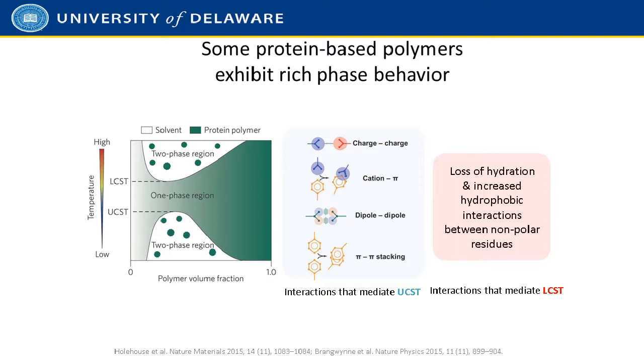If we go back to the one-phase region and instead increase temperature, one traverses the lower critical solution temperature, in which phase separation occurs as a generally hydrophobic molecule becomes less solvated and then forms a polymer-rich phase inside a solvent-rich phase. So we can take advantage of these individual side chain interactions on our protein, as well as overall hydrophobicity, as a way to tune these phase separation processes.